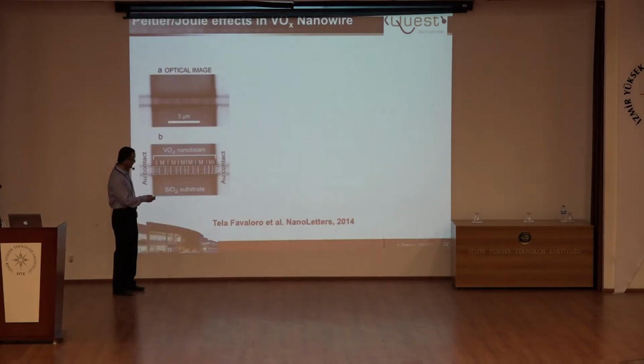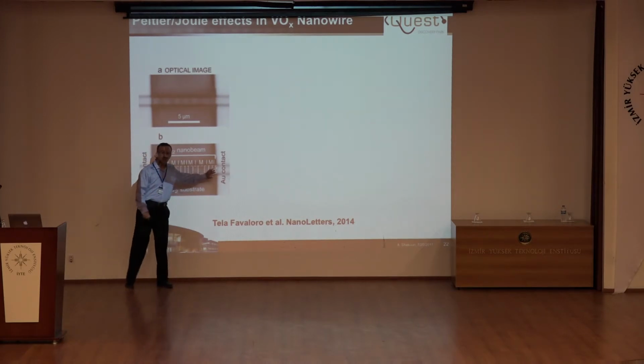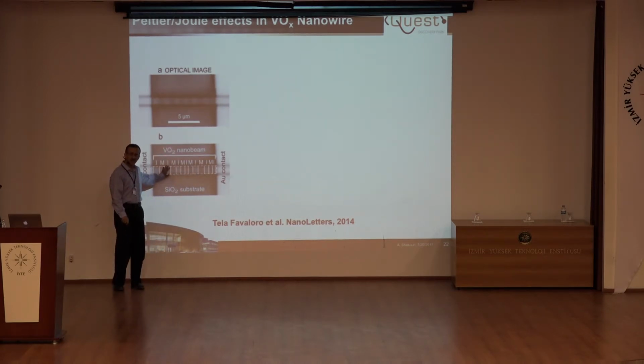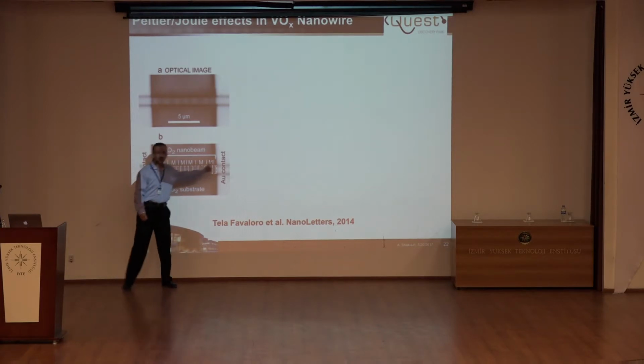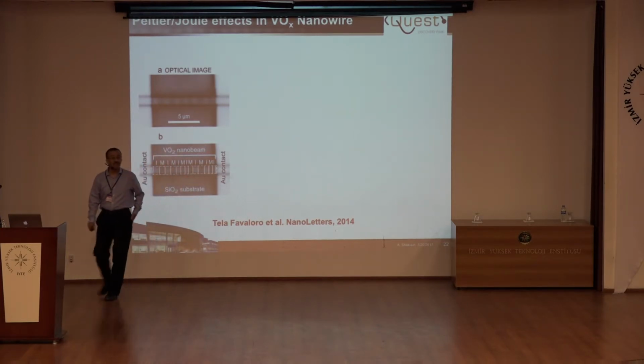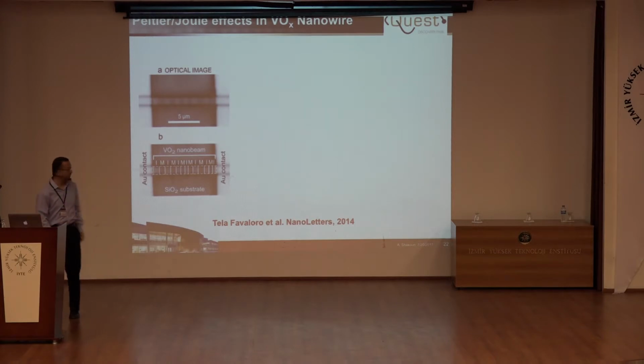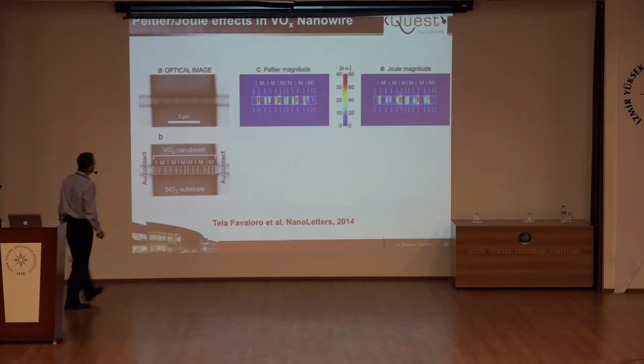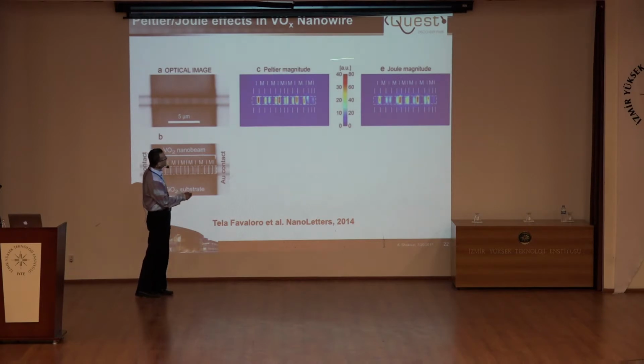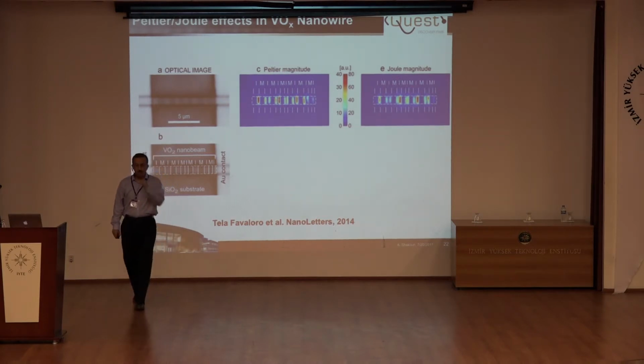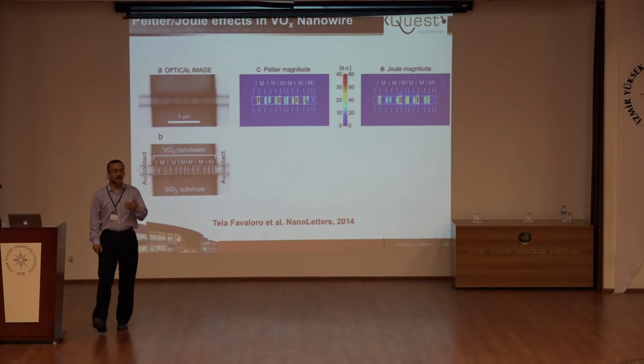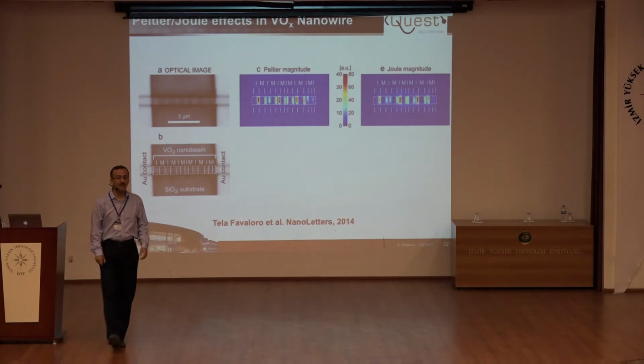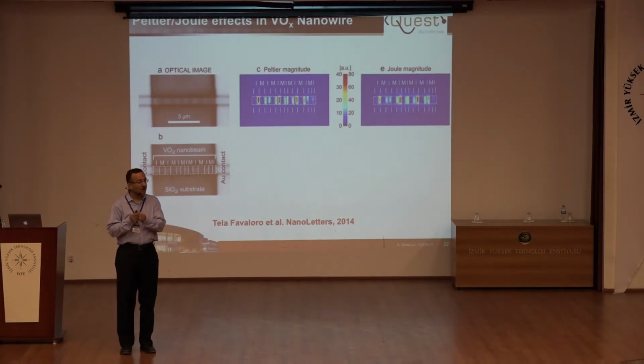And I can send current through this. The question is, how do I know these exist? If I only measure the resistance from one end to the other, I have an average number. You don't know the domains. Here are the thermal images of the same device for Peltier and the Joule. Very quickly, when a current flows inside the device, the current causes dissipation, and this dissipation, which is the Joule effect, locally heats the device. That's what happens in a resistor.